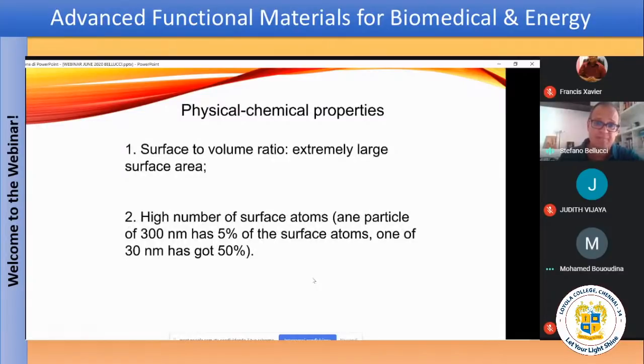What is the reason for it? It's essentially one very simple fact, and is connected to the large ratio of surface divided by volume of these objects. This yields a very large surface area for nanoparticles. To fix ideas, imagine that the number of surface atoms in a particle of 300 nanometers diameter is only 5%. Whereas if you scale down by factor 10 to a nanoparticle of a diameter 30 nanometers, then you get half of the atoms concentrated on the surface.